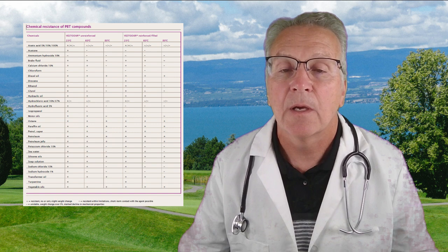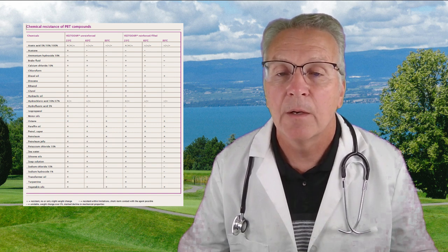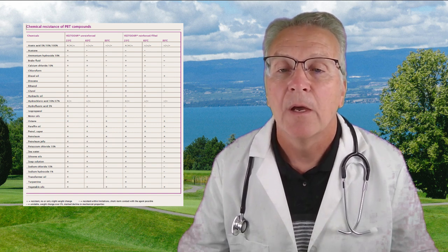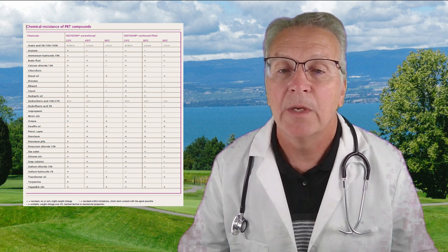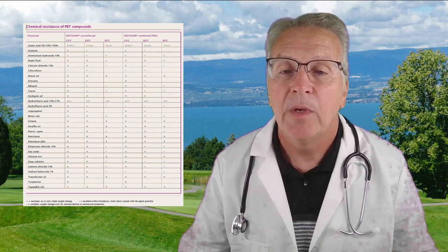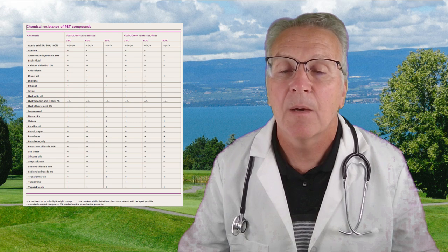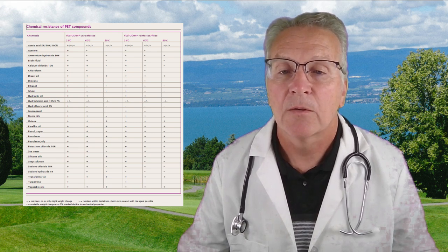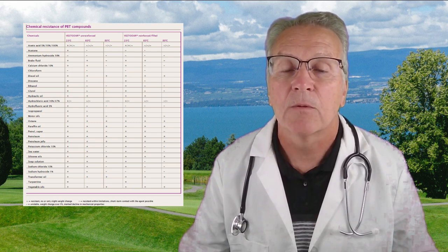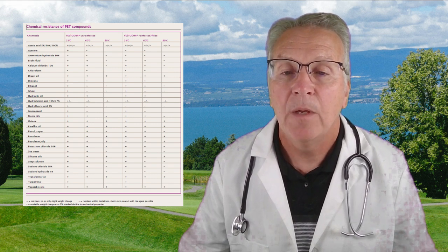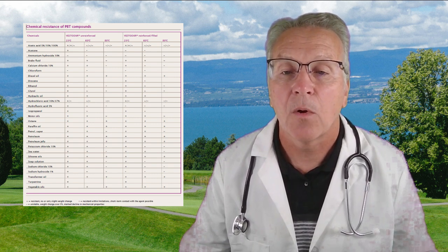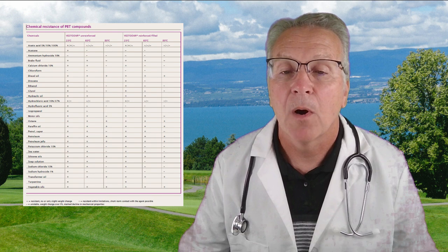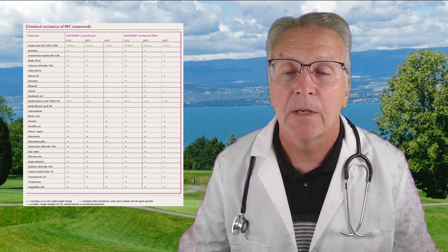On your screen, you see the chemical resistance of filled and unfilled polybutylene terephthalate using chemicals tested at 3 test temperatures. PBT is resistant to many chemicals at room temperature, yet its resistance many times lessens with increasing temperature, and PBT struggles in the presence of chloroform, in which there will be a marked decline in mechanical properties.